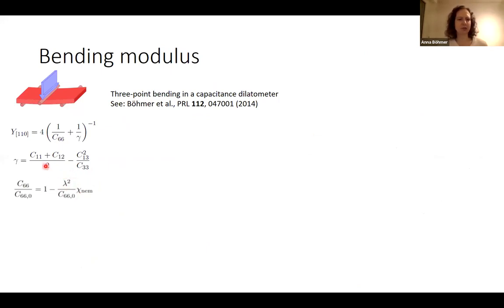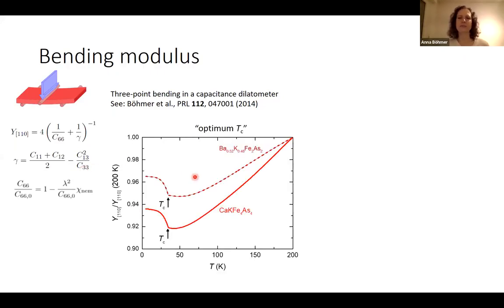What we actually measure is not the shear modulus, but the Young's modulus, which also has some other non-critical elastic constants, and we try to get a handle on that using first principles calculations as input. So let's go to the results. This is the optimum Tc sample, the pure 1144. You see a softening of the Young's modulus, which comes from a softening of the shear modulus, and a significant hardening below Tc. And this is very similar to the 122 that corresponds at similar doping level.